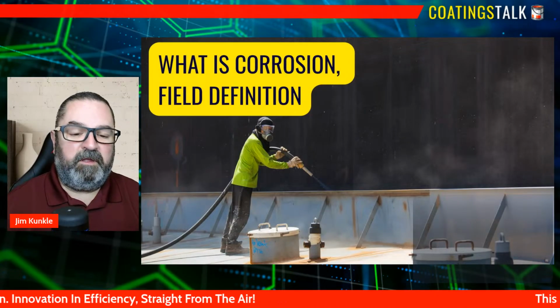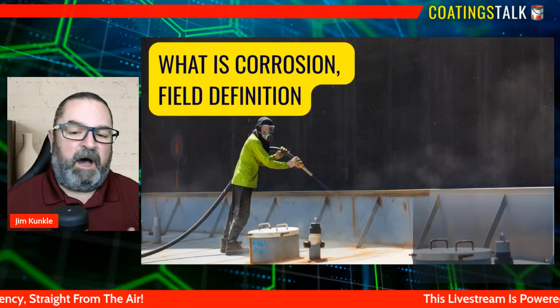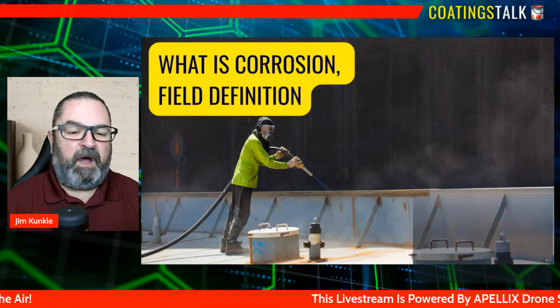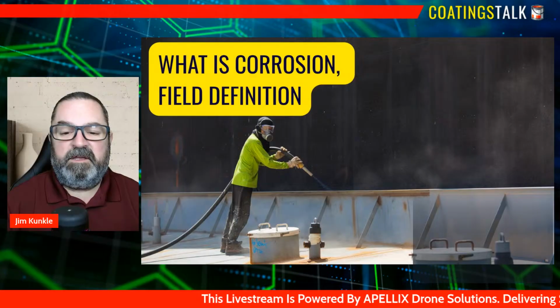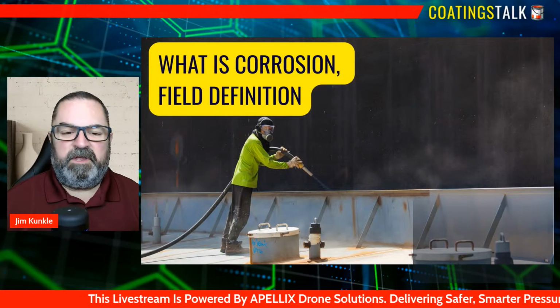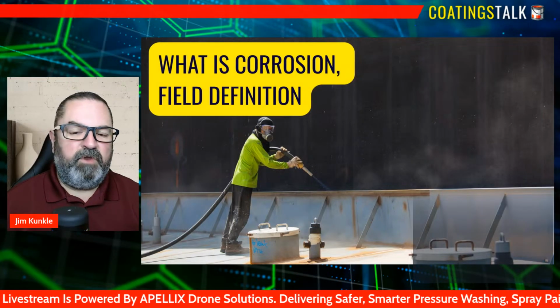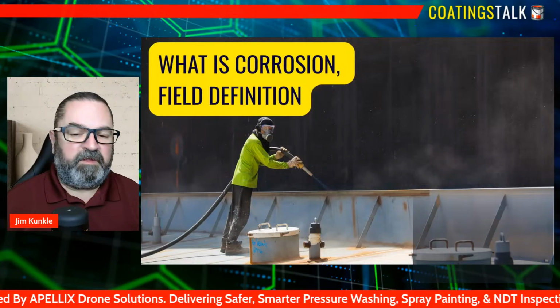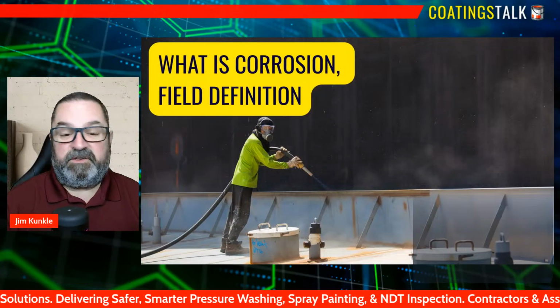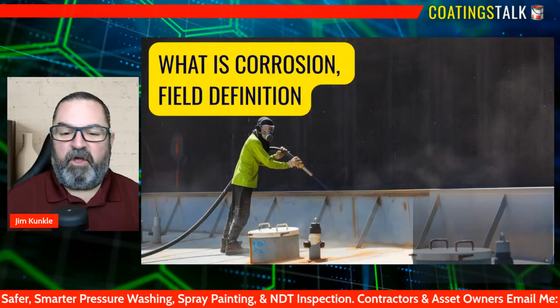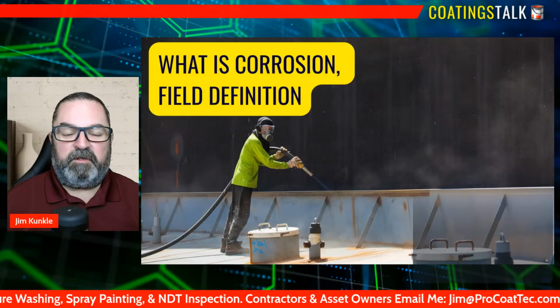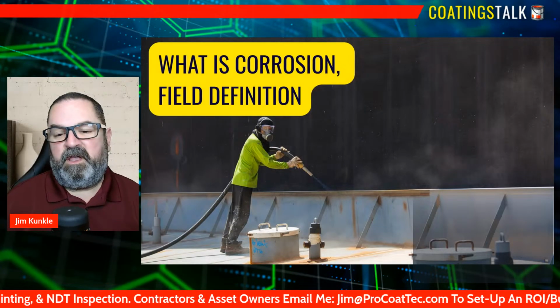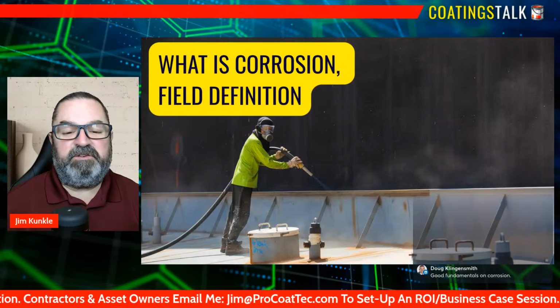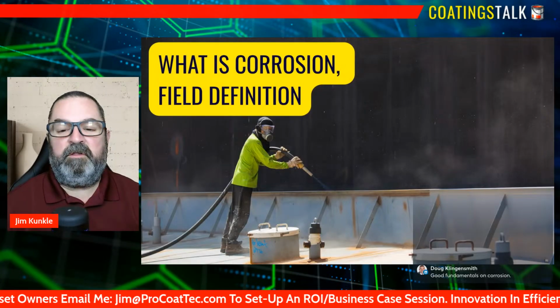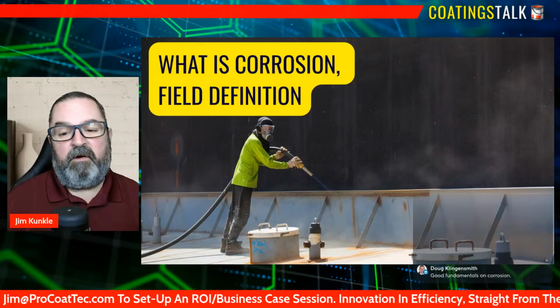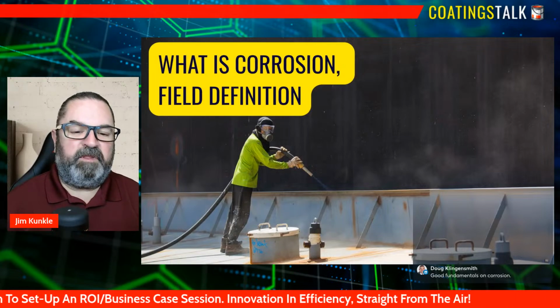This is why coastal assets, including those in industrial zones and poorly drained structures, corrode faster than clean, dry environments. For field professionals, understanding corrosion as a chemical process, not just a visual defect, changes the way that we approach inspection and maintenance. When you know that corrosion begins long before rust appears, you start looking for the conditions that trigger it: standing water, coating holidays, dissimilar metals, or areas where contaminants accumulate. This mindset helps teams catch problems earlier, apply coatings more effectively, and also protect assets with greater precision.